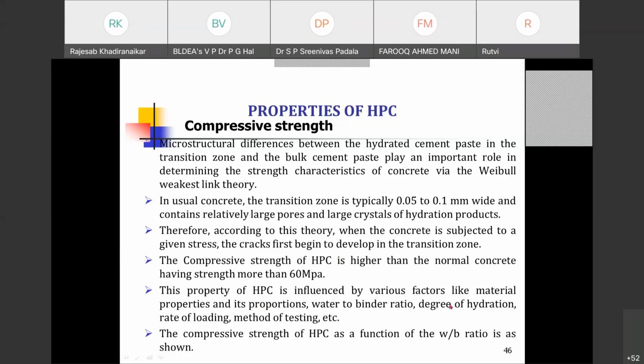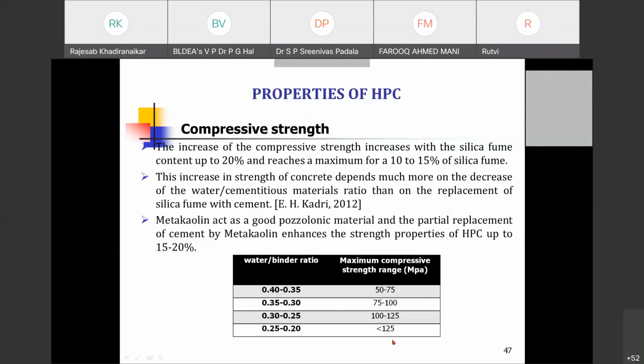This property is influenced by various factors like material properties, proportions, water binder ratio, degree of hydration, rate of loading, method of testing, all those things. Water binder ratio effect also you see. Based on the water binder ratio, they are also classified. The compressive strength increases with the silica fume content up to 20%. Of course, the optimum is 10 to 15%. Very few people have gone beyond 20% because beyond 20% there is no pronounced effect on the strength. So that's why normally in the range of 10 to 15% we use it.